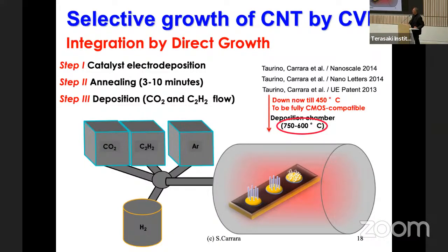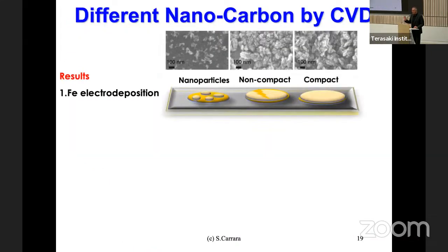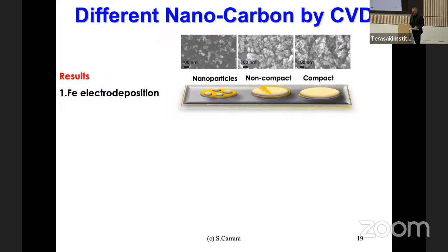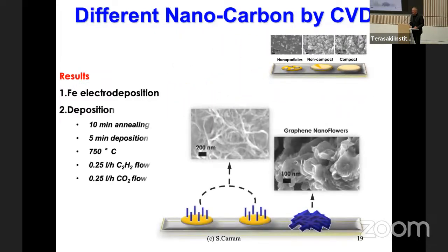But years ago, I had a quite clever student, who also came for a period to Ali's lab in Boston, Arianna Taurino, and she developed a smarter way to set down the temperature, growing by successive CVD depositions. So we can do it, but it's not that easy. If we follow this process, we can even decide which kind of nanostructure to grow on top of the multi-panel just by starting with different quality of the precursor deposition. We can have from fully compact to very rare nanoparticles of the precursor, in this example, the iron. And then depending on the quality of the precursor, we can grow carbon nanotubes or nano petals, kind of rose flowers, where every petal is made by a graphene layer.